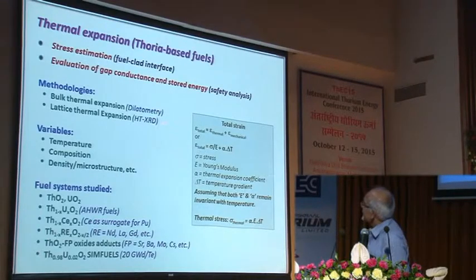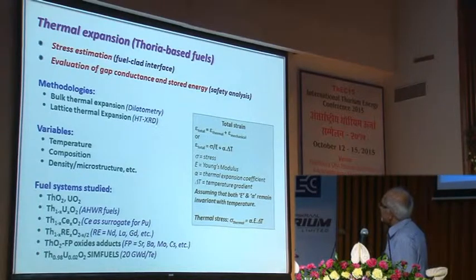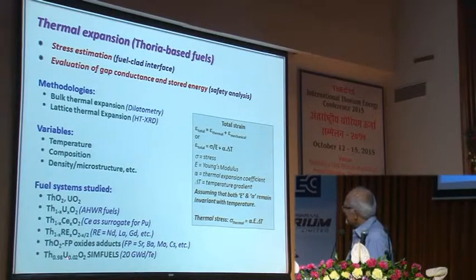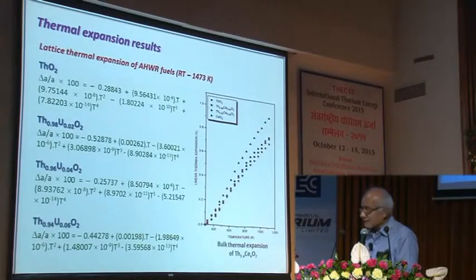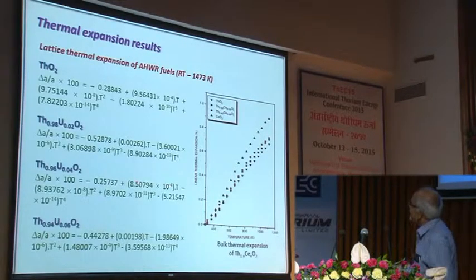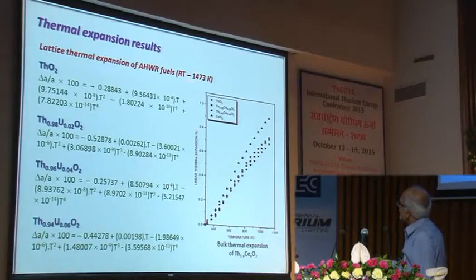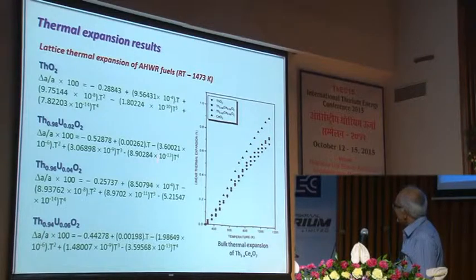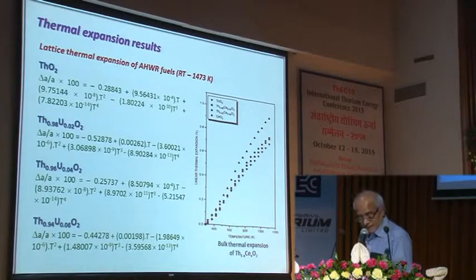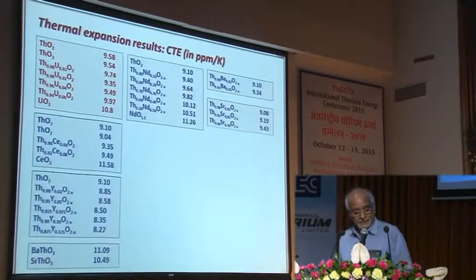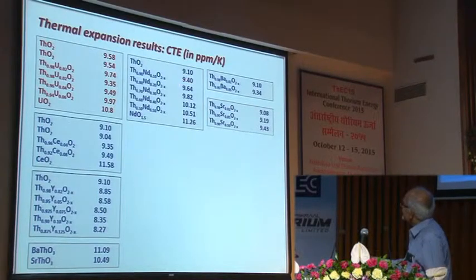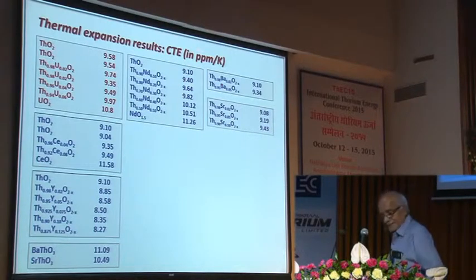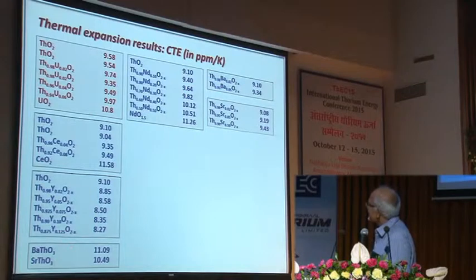The thermal expansion is required for the stress estimation and also for the gap conductance and the stored energy. The methodologies followed here are the bulk thermal expansion and lattice thermal expansion. The variables are temperature, composition, density, microstructure, and a host of fuels have been studied in this program. These are some data that we have generated on the lattice thermal expansion of HWR fuels from room temperature to 1473 Kelvin. And this is data for the bulk thermal expansion with the thoria ceria fuels. And you can see here the coefficient of thermal expansion in terms of ppm per Kelvin. We have studied all this, including this here.